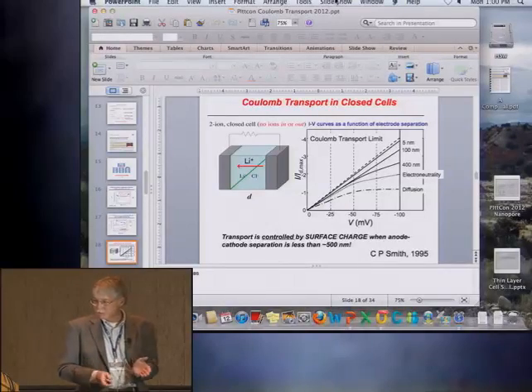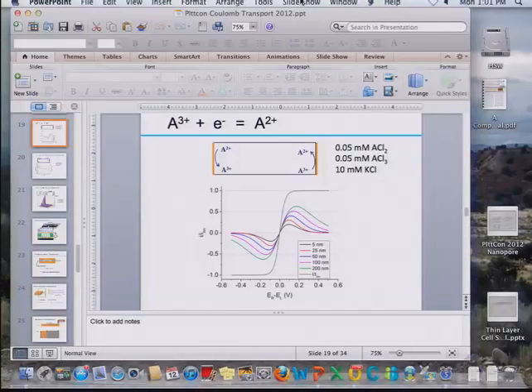But let me tell you the truth here. These calculations correspond to the charging of a lithium-ion battery. And what they would say is that the overlapping double layers greatly enhance the rate at which you can charge a lithium-ion battery. But if you do the calculation for the reverse chemistry, the discharge of the battery, you get just the opposite effect. Instead of the current being enhanced by a factor of 4, the electrical fields just nail the current and it essentially goes to 0. So the message here is that as you make cells thinner and thinner, some very unusual transport behavior results, and we've been trying to demonstrate this experimentally.